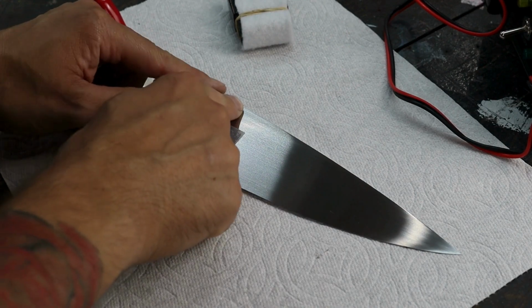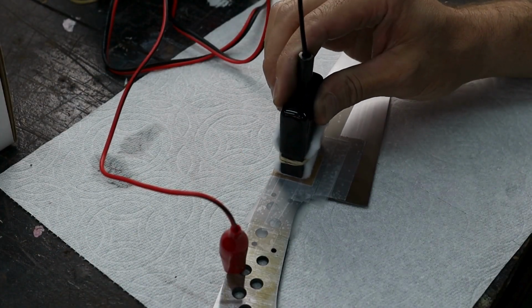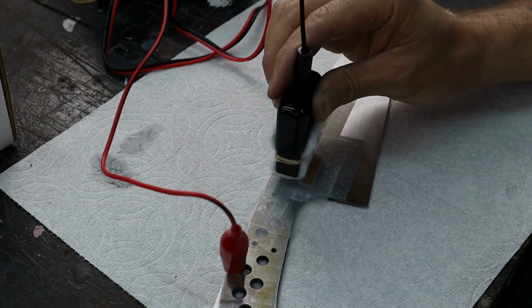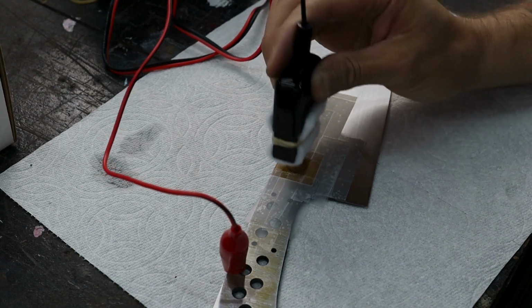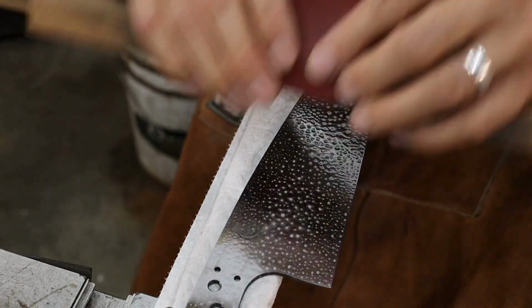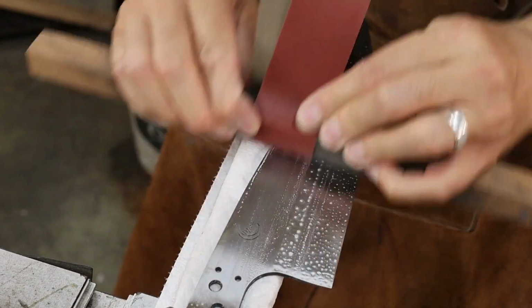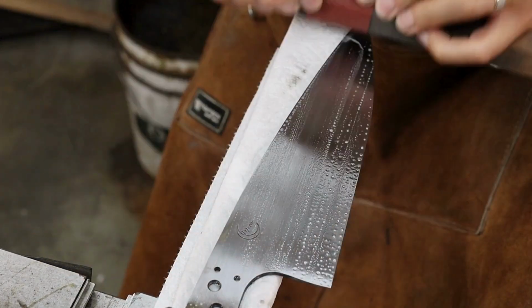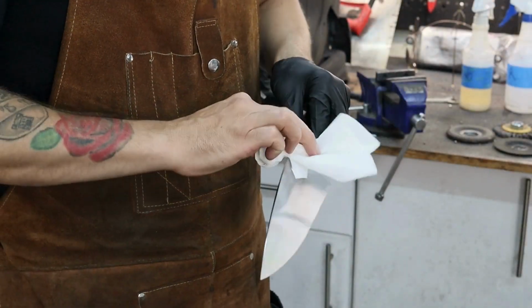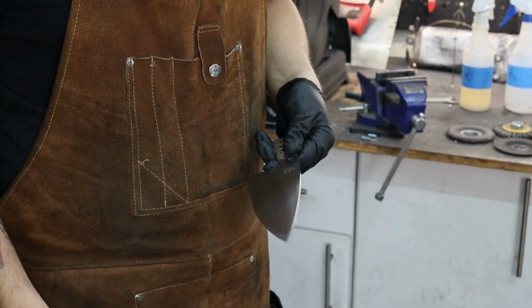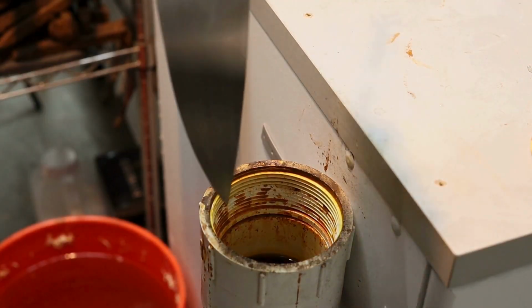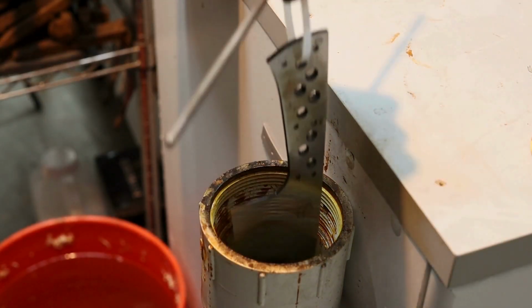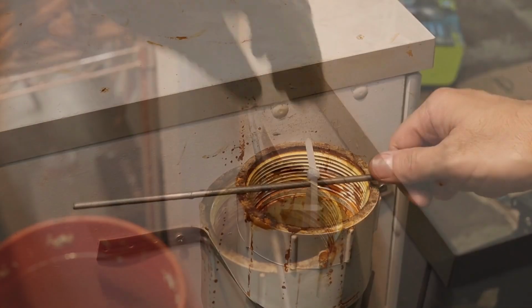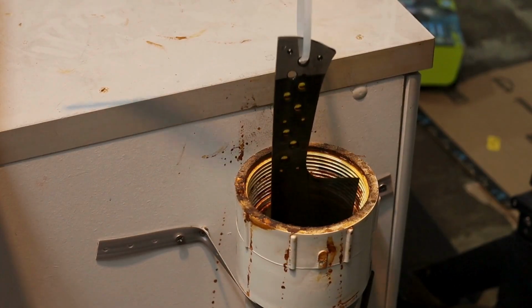The austenitizing temperature, meaning the specific temperature required to dissolve the carbides for 1084 steel, is around 1450 to 1480 degrees Fahrenheit. I quenched these knives at 1475 in Parks 50 quench oil that was heated to around 120 degrees Fahrenheit. If you're quenching multiple blades, it's important to keep an eye on the temperature of your quench oil. I think the specified temperature range for Parks 50 is something like 100 to 150 degrees Fahrenheit.